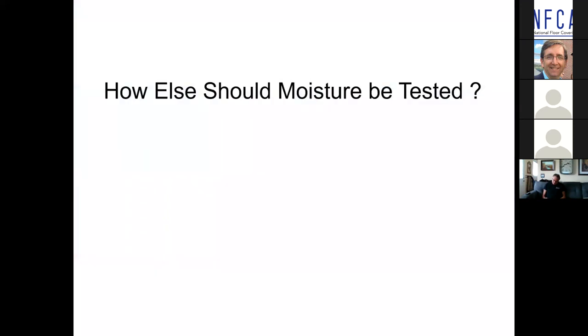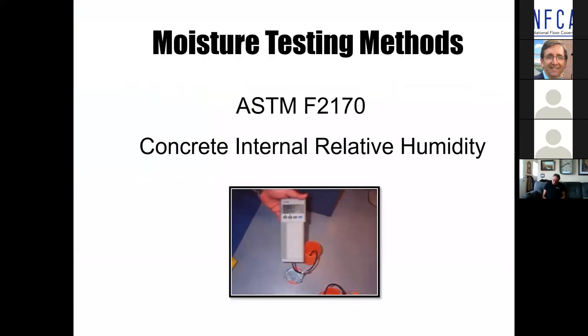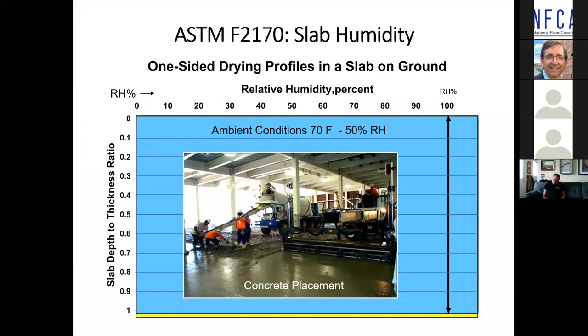That's why we adopted the European method. Most Europeans don't use calcium chloride. They have a calcium carbide test, but relative humidity testing is the norm, and has really become the norm, at least in the United States. When that concrete hits the ground, day one, it's 100% relative humidity, top to bottom. No question about it. And here we have an ambient condition of 70 degrees Fahrenheit, 50% relative humidity.